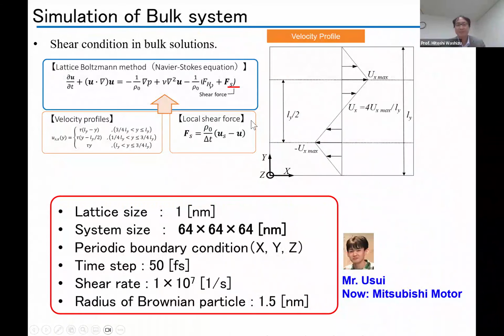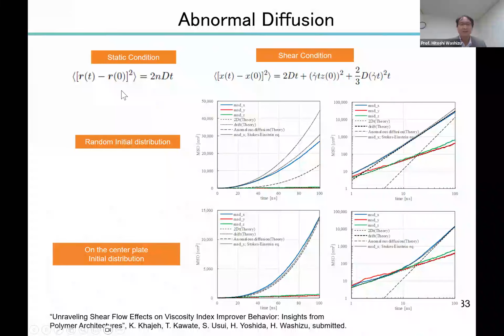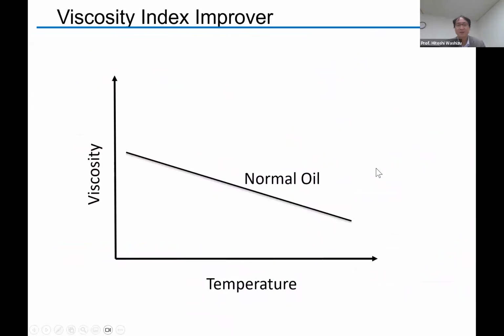So this is an example for the shear. In the static condition, the diffusion coefficient, sorry, the mean square displacement depends on t, but here in the shear condition it goes as t cubed. This is named abnormal diffusion, and we could reproduce this and so on. And one application to oil is the viscosity index improver. I was working in the automotive industry, so the viscosity of oil has temperature dependence.